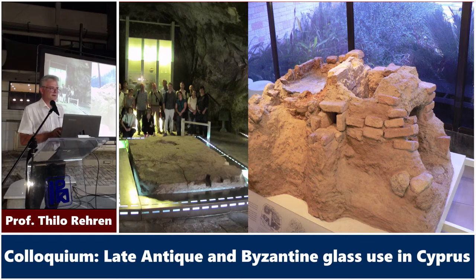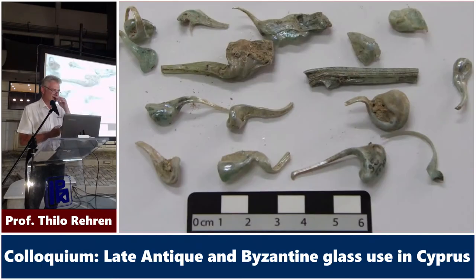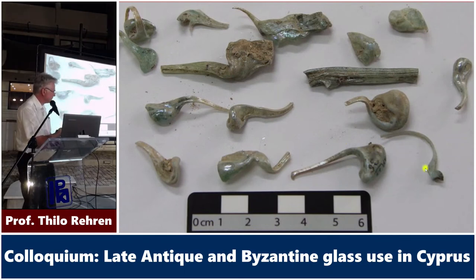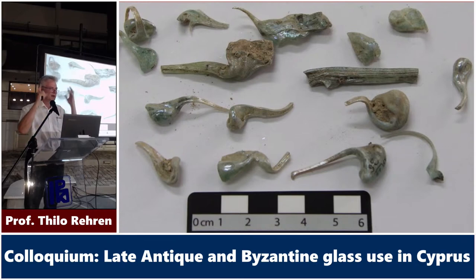And that there was a glass working furnace is clear, because in Limassol, among the material, there's a lot of these drips and drops and drawn out bits of glass which are very diagnostic of the glass worker testing: is my glass hot enough? Is it the right consistency to blow as a chewing gum bubble, to blow into a nice, beautiful object? Or do I need to put on a bit more wood to make it even hotter to get to the right temperature? So somebody clearly was working glass in Limassol. The question is, what type of glass and where did they get it from?